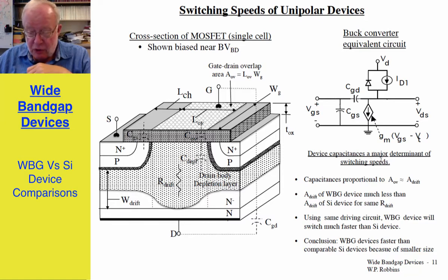And these capacitances are proportional to the overlap area that I've defined here, which is approximately the area through which current flows through the drift region. The area of a drift region for a wide bandgap device is much less than that of a silicon device if you assume the same drift region resistance. And if we're thus using the same driving circuit, the WBG device will switch much faster than silicon. The conclusion is wide bandgap devices are faster than comparable silicon devices, primarily because the much larger breakdown field strength allows the cross-sectional area of the wide bandgap device to be much smaller than that of a comparable silicon device, thus much less capacitance, or in the case of bipolar, much less stored charge.